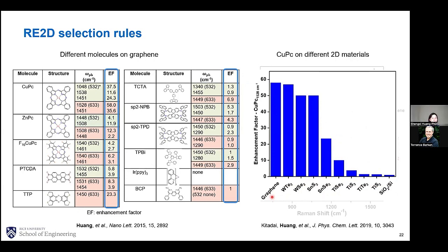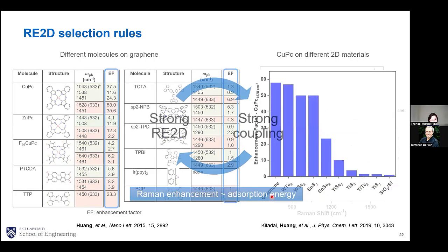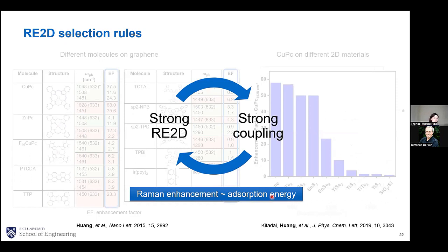So far we have seen that the RE2D effect is strongly related to the coupling strength between the molecule and the 2D material. And actually, for the case of Janus TMD, we can see Janus can provide a stronger interlayer coupling strength with the molecule for certain conditions. So the vertical dipole in Janus can indeed tailor the van der Waals coupling with molecules.